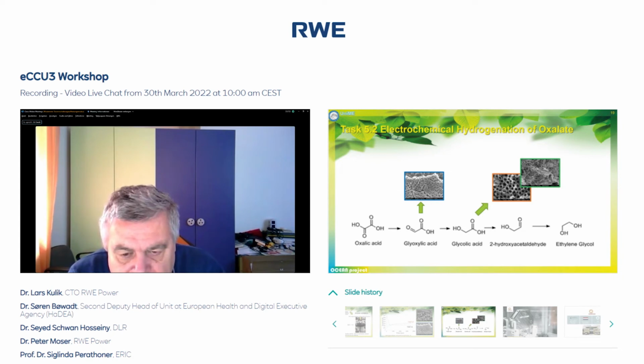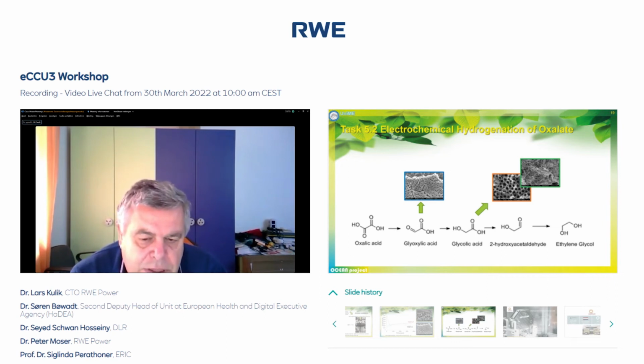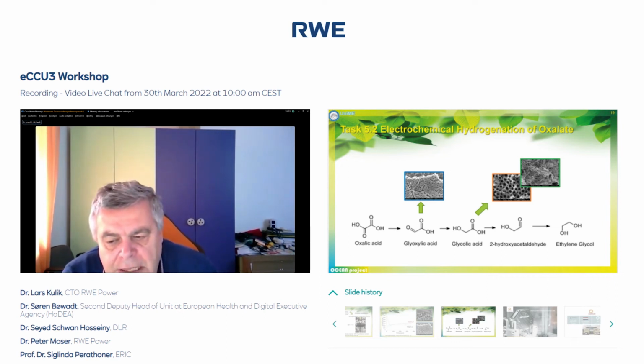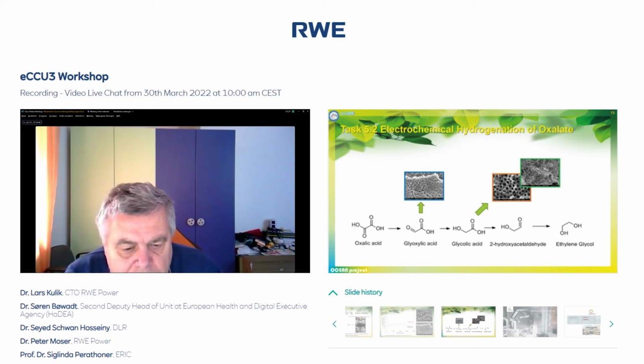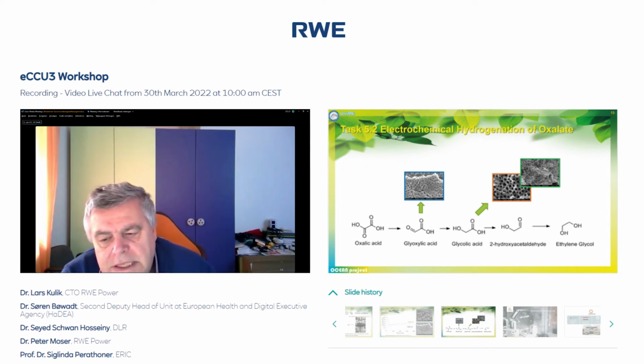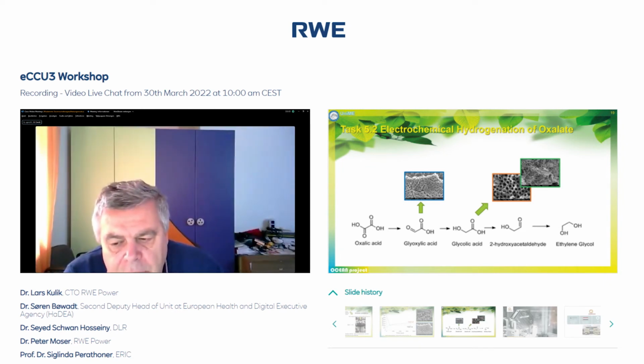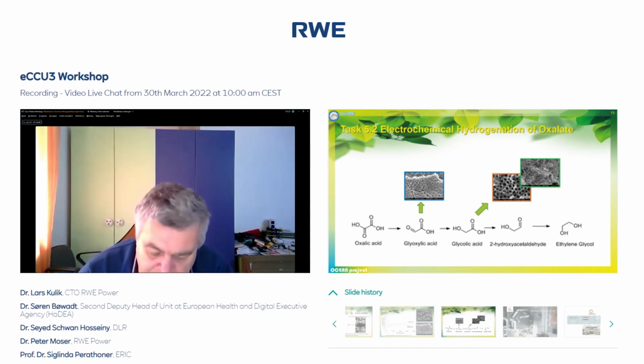We have also tested what happens if we remove these nanoparticles, or if we deposit the nanoparticles on a different substrate, or even on a titanium layer. So it's a different performance. It's this unique combination of this system which is important, and this is also a unique type of selective hydrogenation electrocatalyst. There are few results of this type in the literature, and it is open also to a number of other applications, because the possibility to make electrosynthesis by hydrogenation is a growing area, and there are many other applications.